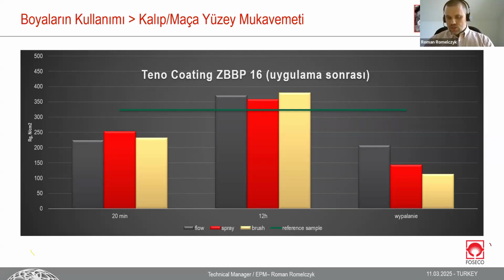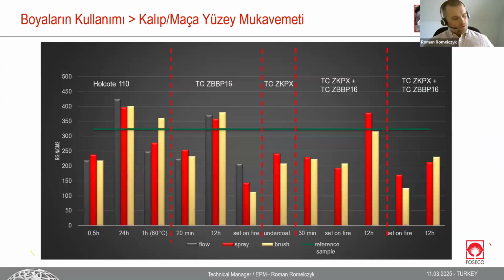When we talk about thin sections of cores or molds as well, we can imagine that the original or wanted strength of the core will collapse, will be very weak. And we have a chance to have breaks, veining, and that kind of defect. Moreover, different coatings were put here, as I said. One is a water-based coating. Another is alcohol. Another is a penetration coating, super diluted, 12 seconds DIN 4 cup. This is a mixture, ZKPX, so penetration coating and external one.